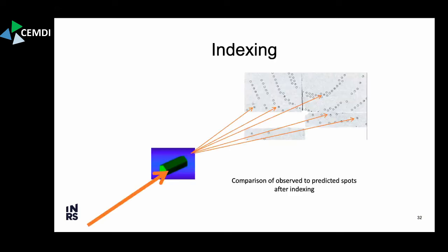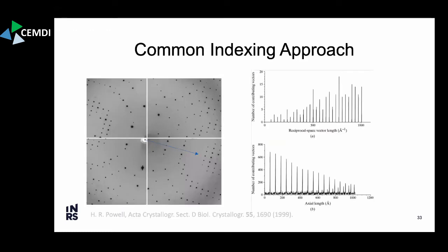moving on to indexing. So indexing is really determining the orientation. As I said before, as you change the orientation of the crystal and the beam, you're going to get different Bragg spots that you observe. And you can use which ones you see to go back and determine what was the orientation of the crystal in the first place. And most indexing algorithms actually are based on a Fourier transform approach. So this works where this is a nice single crystal diffraction pattern.